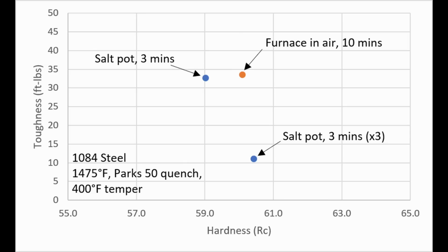warning to knife makers. Many knife makers think like, oh, I'll do this super special heat treatment, and there's a good chance, or maybe only a small chance, that I'll improve the properties, but it's not going to hurt it. And my answer to that is oftentimes it does hurt the properties. So using a more conventional heat treatment is often safer unless you have solid experiments that demonstrate that it's actually improved. And I would not have necessarily expected this result of the lower toughness from the triple quench, but then I tested it and found out that it was worse.